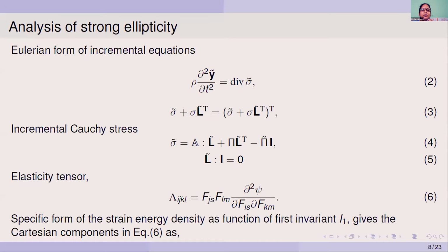The onset of localized damage occurs when the condition of strong ellipticity is violated. And this strong ellipticity, here we associate the loss of strong ellipticity of the incremental initial boundary value problem with the onset of localized damage. So these are the incremental equations in Eulerian form, and this equation 2 gives the balance of linear momentum.